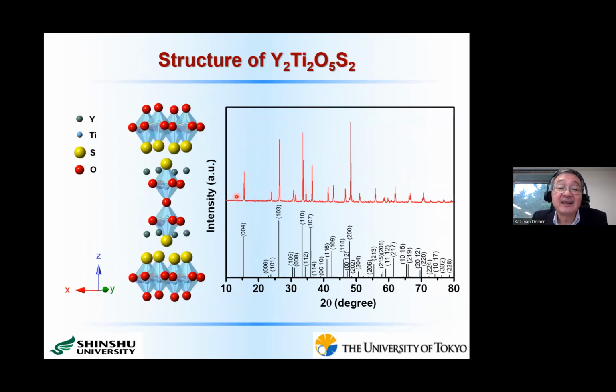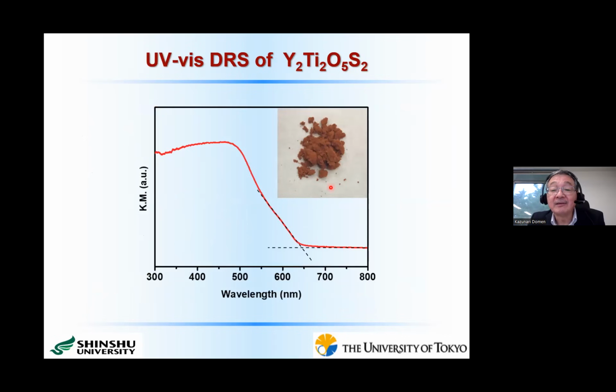This material has a so-called layered perovskite type structure. This yellow ball is actually a sulfide anion. And this is a photograph of this powder material. This is a little dark brown colored powder material. And the absorption edge is extended to about 640 nanometers.